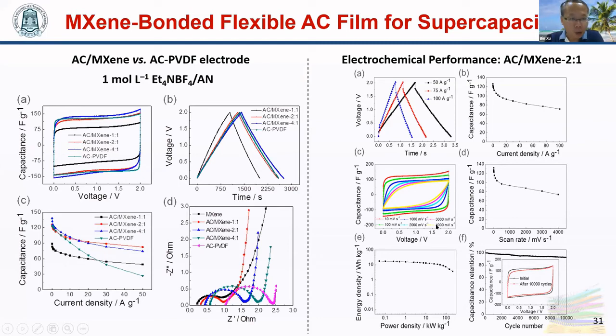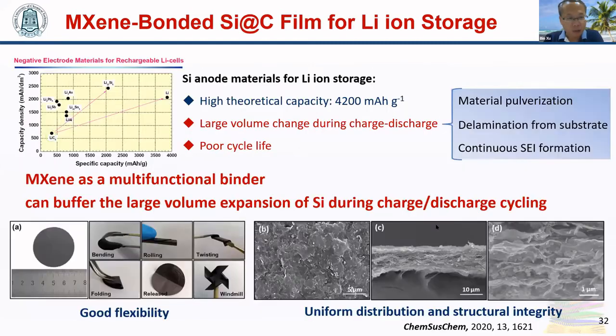The MXene binder can also be used in electrode fabrication of batteries. As we mentioned previously, silicon is a very promising anode material for lithium-ion storage due to its very high theoretical capacity. However, it suffers from large volume change during charge-discharge and poor cycle life. With MXene as a binder, a freestanding carbon-coated silicon film is easily prepared. And this film is freestanding and has very good flexibility.